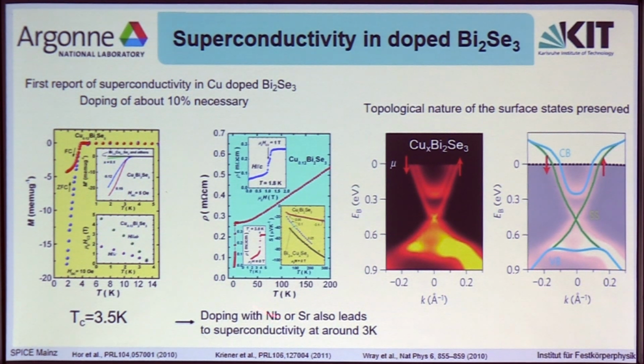Now, doping has also been achieved with niobium and strontium pretty shortly afterwards, and they all show a Tc in about the same range, around 3 Kelvin.